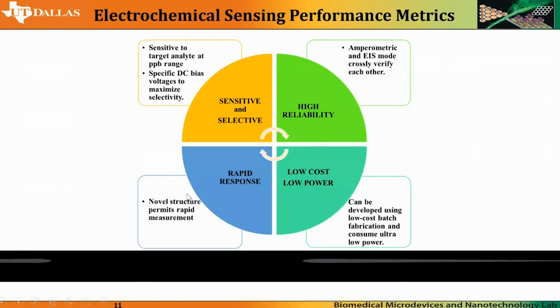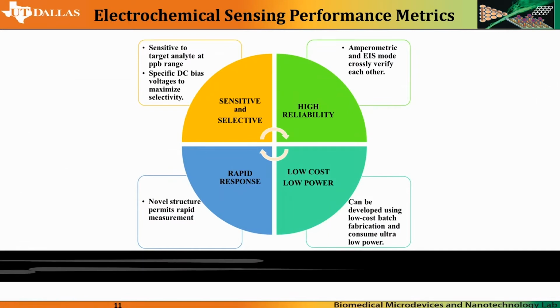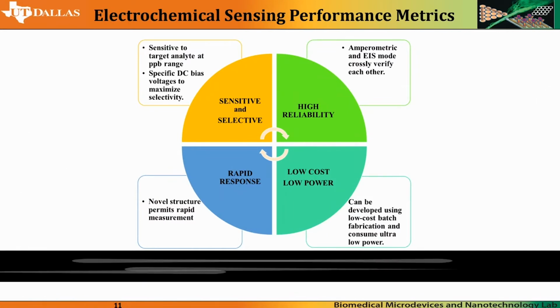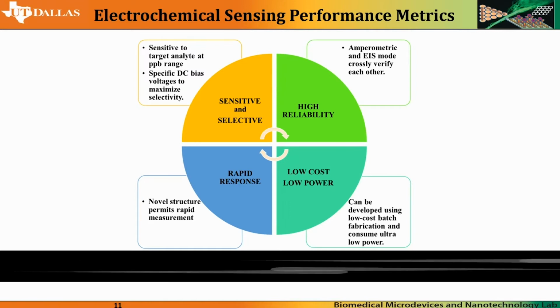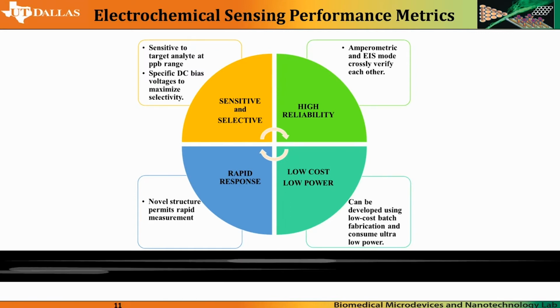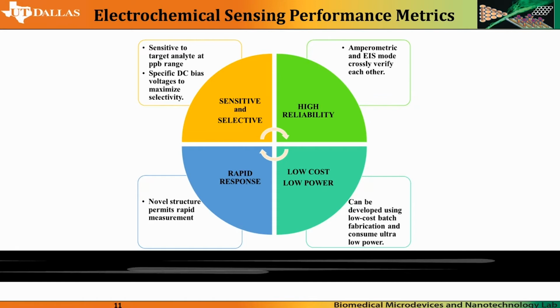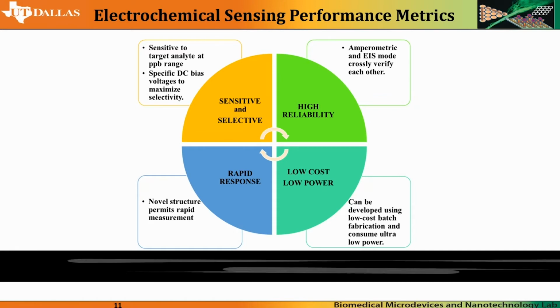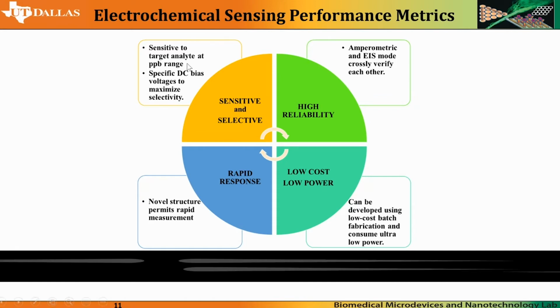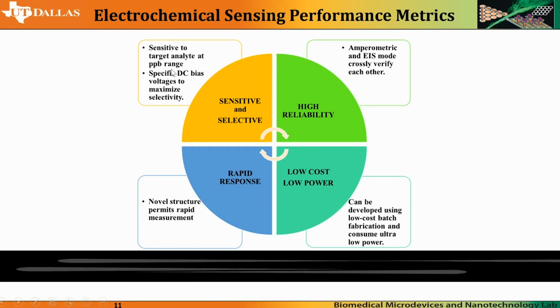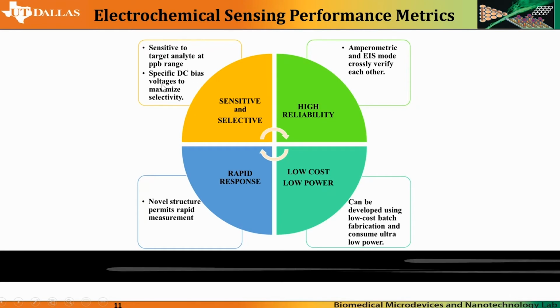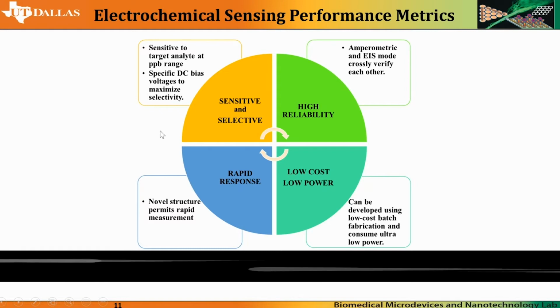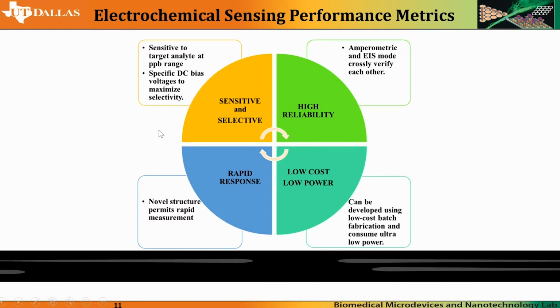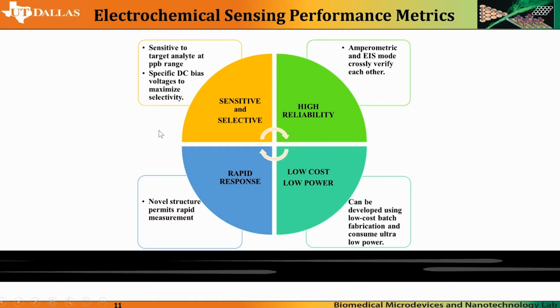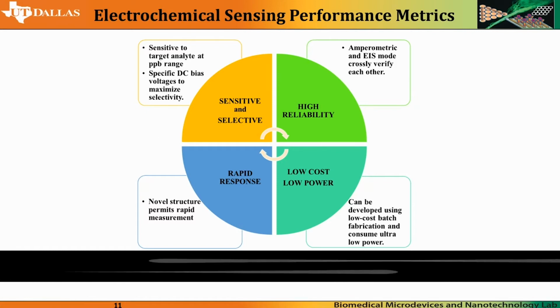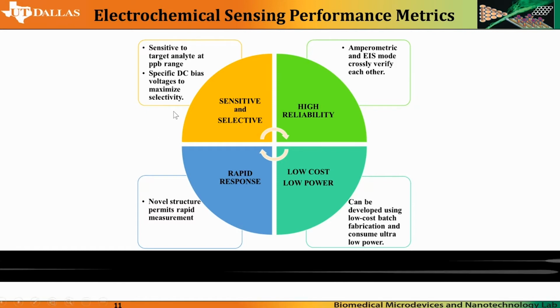Electrochemical sensing performance metrics then. While developing a sensor, you need to hit these four metrics such that your sensor can then be used for point-of-care diagnostic development. Sensitive and selective: the sensing device should be sensitive to the target analyte in the parts per billion range, and use specific DC bias voltages to maximize selectivity, such that it is only selective to the presence of one target compound and is not cross-reactive to other species.